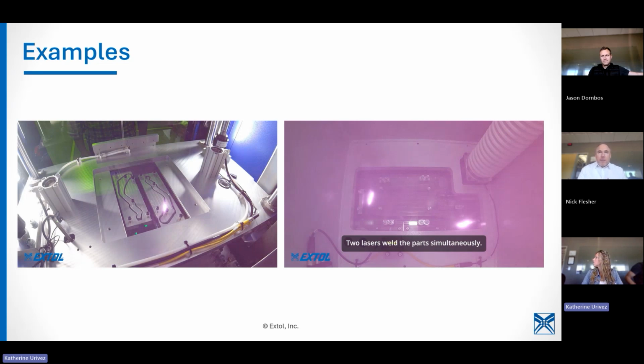That said, it's not uncommon. It's not like 50%, but I would say 10 to 20% of the time customers have designed for ultrasonic, and maybe they're damaging some components, or maybe they have a surface read through. We can clamp just enough to start the weld process. If you're not familiar with ultrasonic welding, you have to have a little triangle to start the weld process. We can't even do energy directors with laser welding, but most of the time, in fact, we recommend